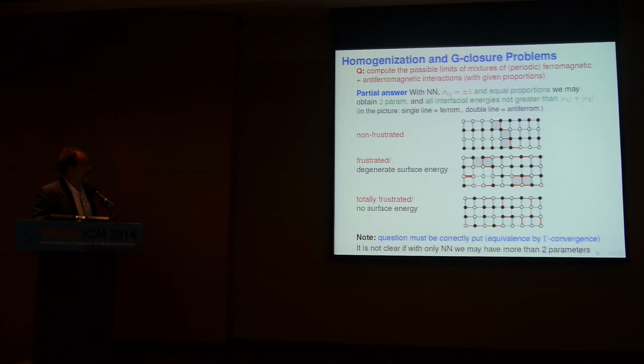For example, even the simple homogenization problem, where you want to describe the limit when you mix ferromagnetic and antiferromagnetic with equal proportion. For example, you can obtain something which is non-frustrated and has a surface energy of crystalline type, or which is frustrated and has an energy only in one direction, so it's a degenerate surface energy, or totally frustrated. Okay.